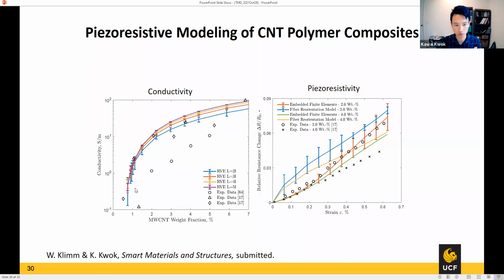This shows the expected behavior: the conductivity goes up once you hit a certain percolation threshold. If you don't have enough carbon nanotubes, it does not form a conductive network, so the conductivity is very low. But once you hit that critical point and the network is percolating, you have a very sudden jump in conductivity. Adding more will increase it, but not by a lot further, so there's a marginal benefit. You see there are some triangles here. Those are the data points from the literature, and they are in quite good agreement.